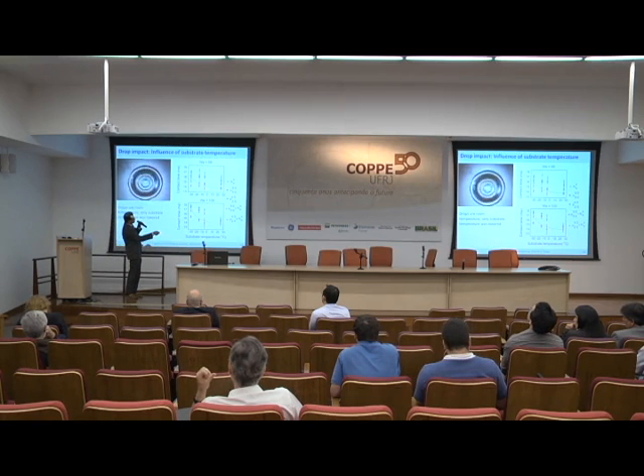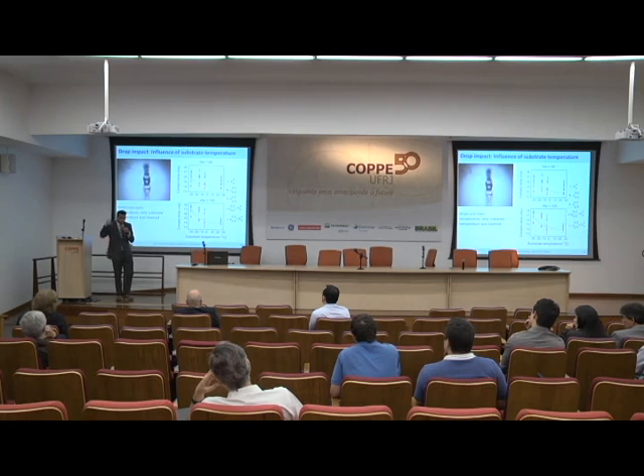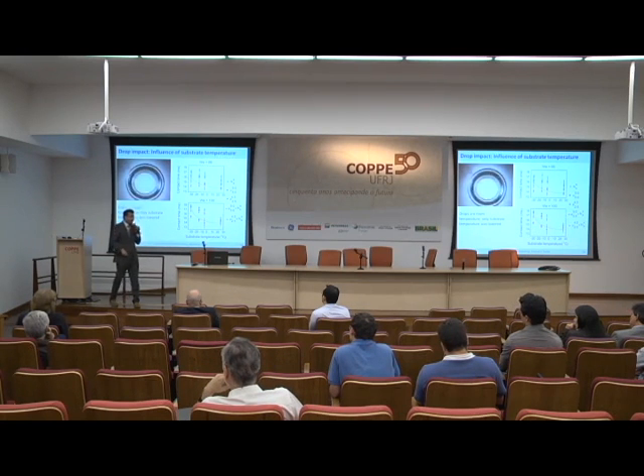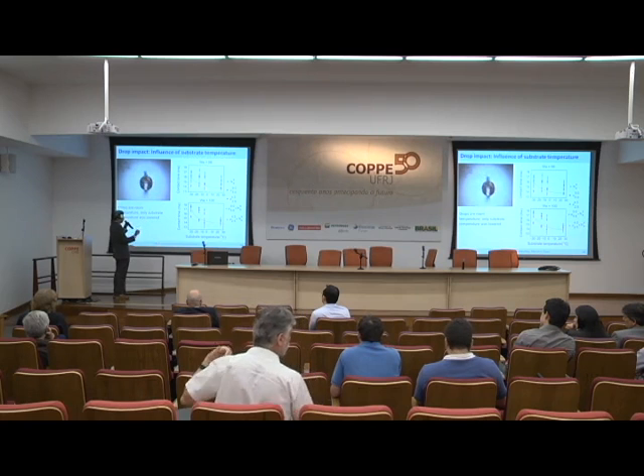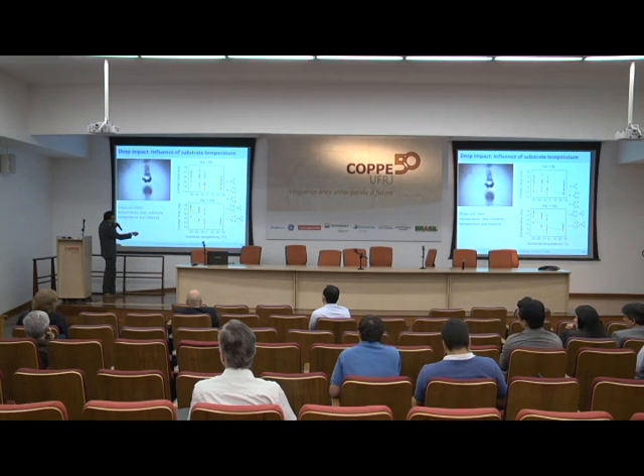And if you look at two surfaces, let's say two microstructured surfaces, which have a pillar diameter of about 5 micron and spacing of 9 micron in this case, and in this case 2.5 micron and 4.5 micron spacing, the beauty of these numbers is, if you look from the top, the solid fraction that the droplet sees is exactly the same. So meaning, if I put a droplet very gently, it sees the same amount of solid. I've just adjusted the diameter and the spacing, okay? Now, those two, they are overlapping here. This black guy and the blue guy, they are overlapping here. Within the error of the measurement, there is no distinction between them. If I go to slightly higher Weber number, the droplet does come off, but here's the black fellow, and the blue one is hidden in here.